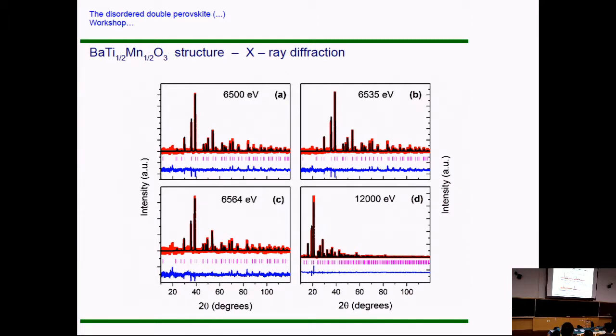So what you do is try to do X-ray in a little bit smarter way. You simply change the energy close to the absorption edge of the manganese, for instance, and that gives you what we call anomalous diffraction. Essentially, since you are close to the absorption edge, the intensity will be anomalously large, right? So you can distinguish the reflections that come from manganese or titanium, and so on. This is a way to try to distinguish a little bit. And then we test our model, and systematically what always gives you the best statistics, the best fits that you can get from the Rietveld refinement is this proposal, right?